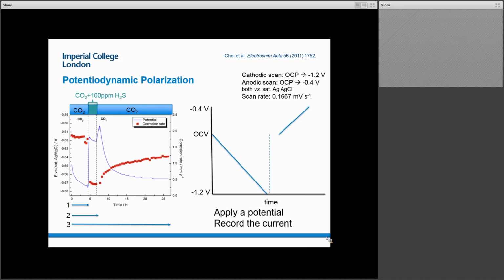And so the answer that they first take in that first leap is they talk about potentiodynamic polarization. So this is one of the most, in some ways, straightforward experiments. At the end of each stage of their experiment, they decided to run this. The way it works is they're going to start at their open circuit potential, which obviously is different depending on the stage they're at. They introduce first a cathodic scan, then allow the system to return to open circuit, and then introduce an anodic scan. So in effect, they're going to apply a potential and record the current.